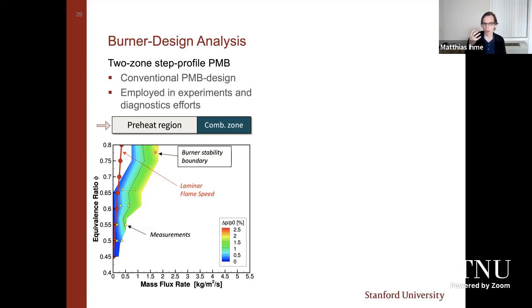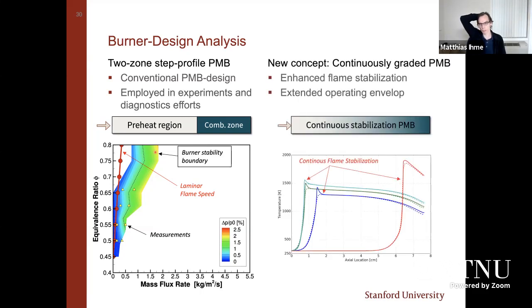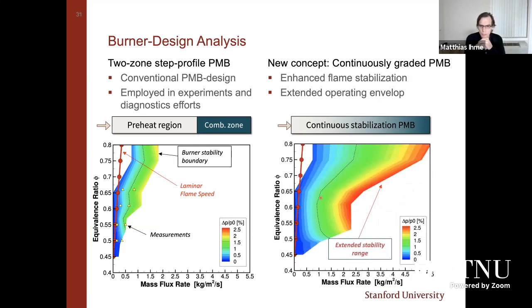Now, this is our prior burner that I showed you experimentally in the experimental results in the first part of this presentation. If you're now looking at this continuously stabilized burner, where we're changing the porosity and the pore diameter throughout the burner, you can see right away that the flame is now not anchored at this interface anymore. It can float freely throughout the burner, and depending on the mass flow rate and the operating conditions, you can achieve different combustion zones. And this makes it rather interesting, since now I have a much broader range where I can operate the porous media burner. This translates to a significantly extended operating regime.